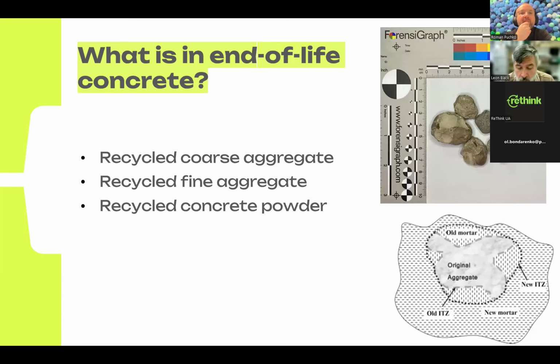Well, if we're going to do things with end-of-life concrete, we need to know what it is. And we can consider end-of-life concrete comprising of three components. We have recycled coarse aggregates. These are gravel, stones, between 4 millimeters and typically up to 20 to 40 millimeters in diameter. Then we have recycled fine aggregates. It has particle size from 150 microns to 4 millimeters. And then we've got recycled concrete powder, so a fine material less than 150 microns in diameter.